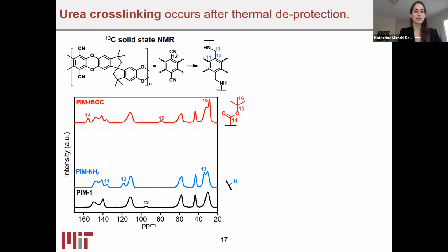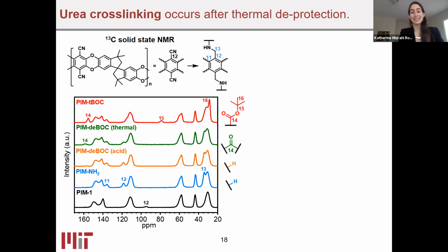You can also see the carbonyl peak 14, which appears at around 156, and that is associated to the carbonyl of the TBOC group, which again was encouraging that we had formed the correct material. After deprotection, however, you can see two interesting effects. One is that we do recover most of the chemical signals that are associated with the amine PIM. But also for the thermally deprotected sample, there's an additional peak labeled peak 14 that is not exactly at the same spot as the TBOC peak.